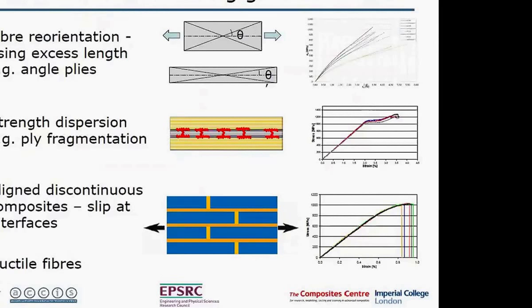So one area is by looking at fiber orientation. You have angle plies, and then you pull them up, and you get a scissoring effect. You can generate additional strain, additional excess length, which can produce strain on top of the basic elastic strain of the fiber. That's one way where you can produce some non-linearity and some pseudo-ductility. Not going to talk about that today.